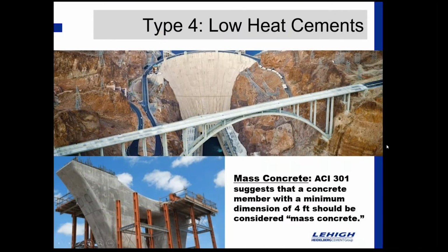And then type 4 is a low heat cement. And again, this is a situation where we're looking at a cement where we're concerned with the heat generated from just the overall mass of the concrete, where thermal cracking becomes an issue. We can limit that amount of heat generation by the use of a type 4 cement. And bearing in mind that mass concrete, according to ACI 301, suggests that a concrete member with a minimum dimension of 4 feet should be considered mass concrete.